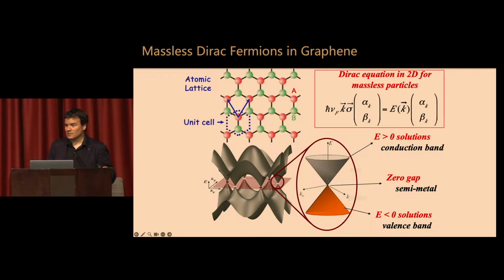And in fact, the equation that governs the behavior of electrons in graphene at those low energies, for which you have this linear energy momentum dispersion, is here. This is the Dirac equation in 2 dimensions for massless particles, which means it is the equation that governs the behavior of ultra-relativistic particles. Ultra-relativistic means zero mass particles, okay? And it's this equation here. So the electrons in graphene do not go at the speed of light. They go at a speed which is actually about 300 times less. It's called the Fermi velocity. But it's constant, independent of their energy. And in that sense, they behave like ultra-relativistic particles.